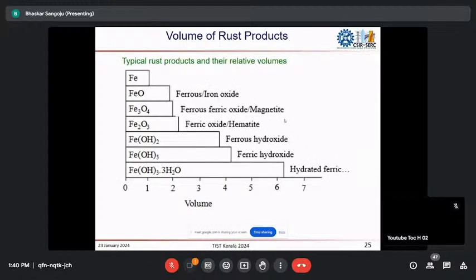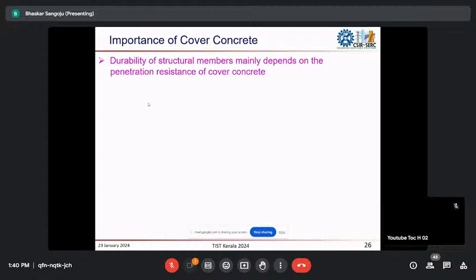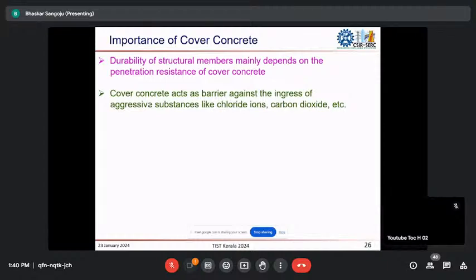And these are the rust products. Different rust products will have different volumes. Because of the increase in volume of the rust product, the rust tries to exert pressure on the outer concrete layer, thereby cracking, delamination, and spalling of concrete will take place. So finally, you will see the exposure of rebar. That is why the cover concrete is very important for durability of a structural member, because that protects the reinforcement bar from the external environment, and also it acts as a barrier for the deteriorating agents not to enter inside the concrete.